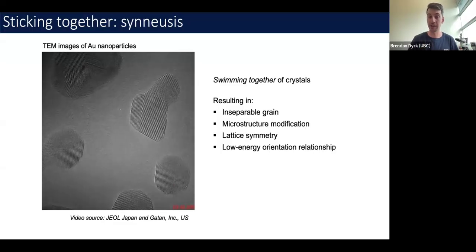They're very strongly attached. There's a very rapid microstructural modification right at that grain boundary. And most importantly, we're going to see lattice symmetry across what were two initial grains. Now we can think about that lattice symmetry in terms of low energy orientation relationships. And we think about this in the sense that any two crystals that come together, whether or not they're the same mineral phase, will have a lower or a higher energy orientation relationship.